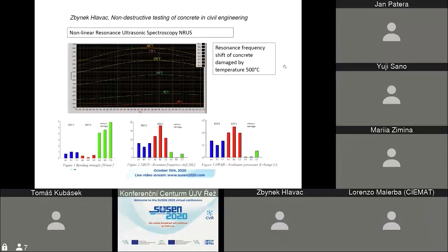What I'd like to show is NRUS, ultrasonic spectroscopy. It works so that I'm increasing amplitude, and the frequency shifts to the left side when the sample is damaged. On the bottom, you can see a comparison between various methods. When I'm doing a bending test, for the samples without damage, the strength is high. When I damage the sample, strength is low.